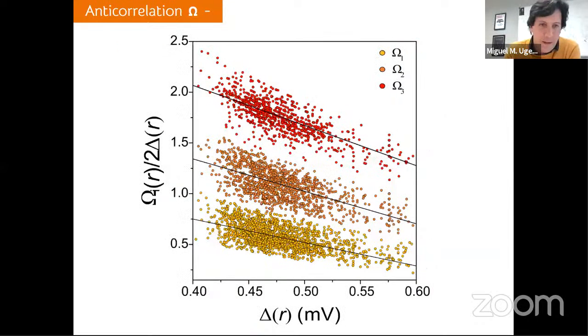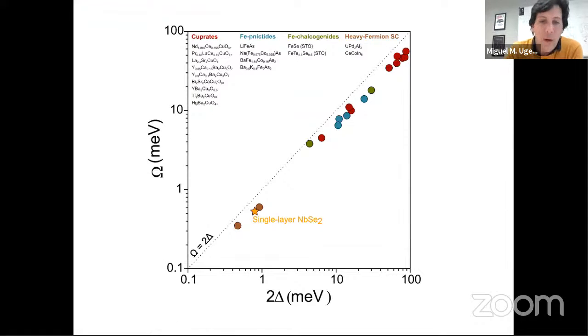Okay, so that's what we find for the fundamental mode as well. It's just below 1 in all the cases. So if we now plot the ratio, or we plot the energy of this bosonic mode against the 2 delta, you see that all these unconventional superconductors lie on this particular line, and this is the case for single layer niobium diselenide.